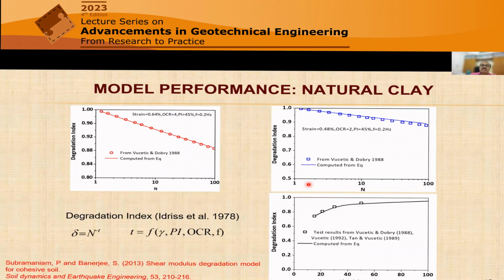So again, we keep on studying our degradation behavior. We saw, as in that 3D plot, that the degradation is a function of strain, PI, over-consolidation ratio, and the frequency. And if we come up with those formulations, we try to do a simulation and compare with the experimental data. Of course, to make ourselves confident about our model, we didn't choose our own data at all. We selected very well established data with varying these parameters, and we used the computed equation as per our development, and we saw it's matching fantastic.